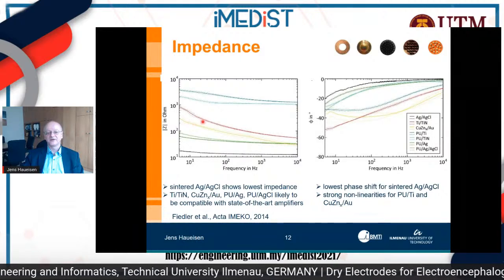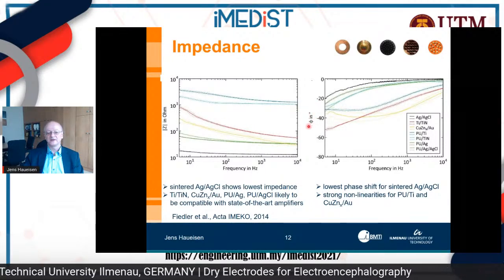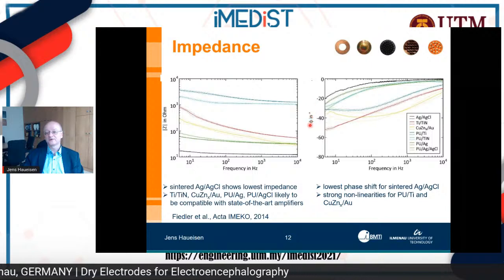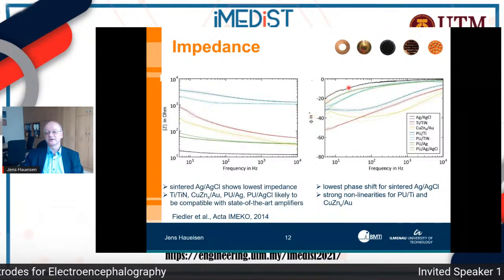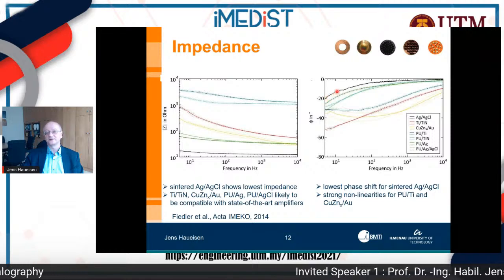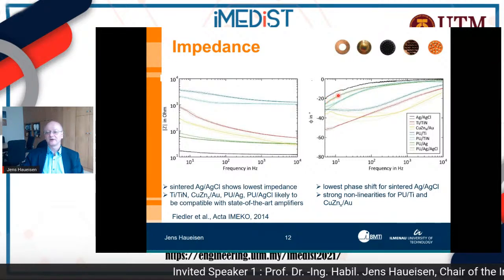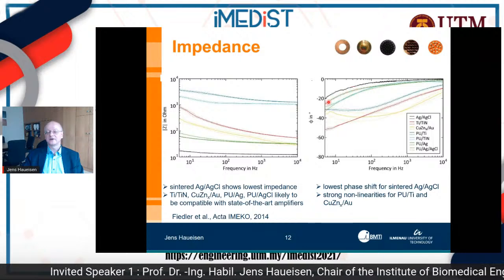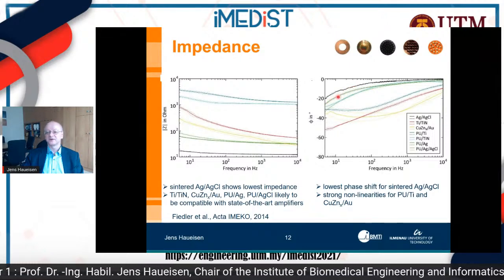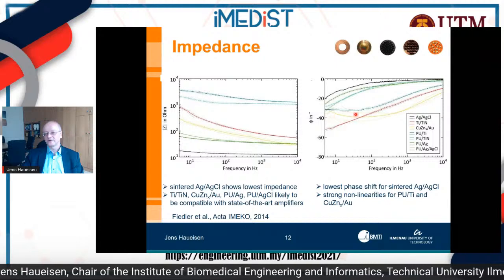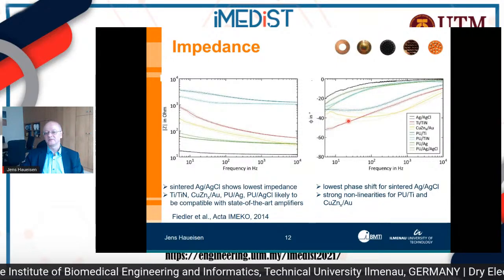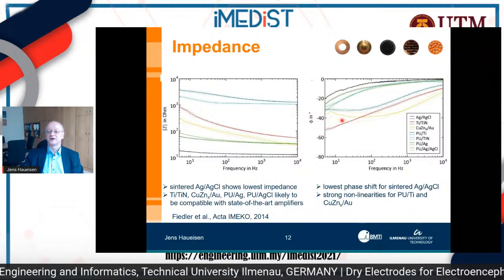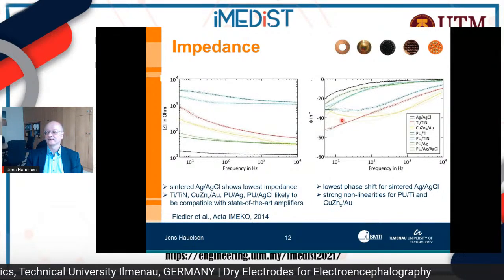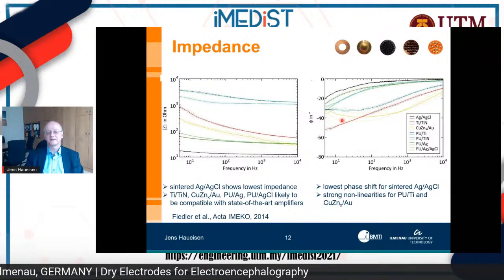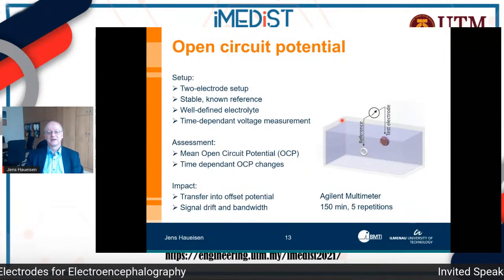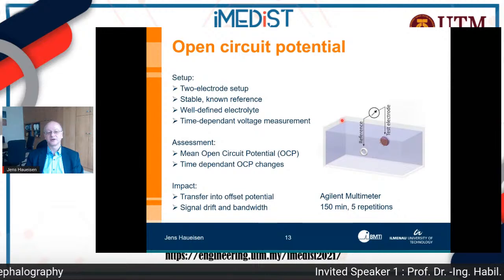When we look at the phase shift which we observed, then again, of course, our gold standard has the lowest phase shift and also the lowest standard deviation. Again, followed by the silver chloride electrode based on polyurethane as a substrate material. And again, you observe here for both the titanium as well as for the gold pins quite significant standard deviations. So this already gives us a hint that the gold pins might not be the best choice, but we'll have a look also at the open circuit potential.